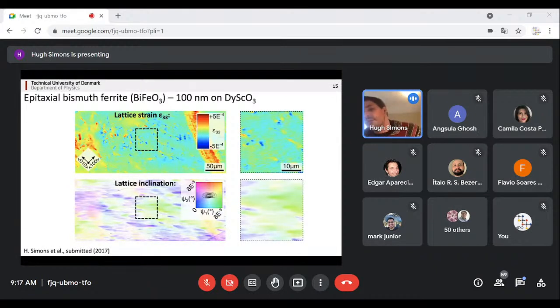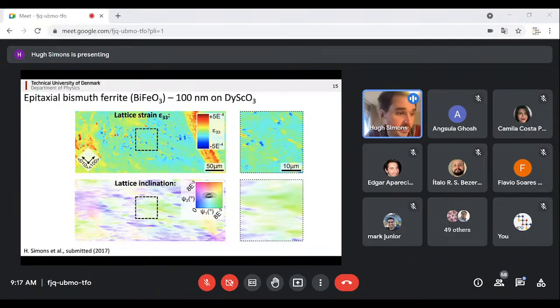So before we looked into aluminium, we thought, okay, let's see if we can find a simpler model system. And so I was talking to some people from my old university who said that, if you want a sample that has very, very few dislocations in, you should take my thin film of bismuth ferrite, because they said this is a near perfect film, there should be no defects in it. And so I put it in our microscope, and we saw all of this strain and misorientation all over the thin film, and it was very clear that this, in fact, wasn't a perfect film, but not just that, we're actually very sensitive to these small misorientations.